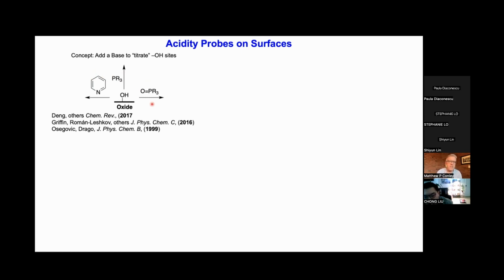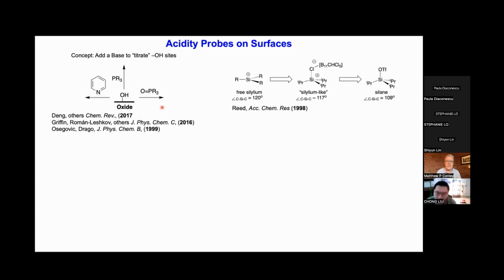Another method that we're interested in, because these are single point measures, but they don't give you all of the information you want, because you get to a point where you protonate the phosphine irreversibly, and then you're losing some characteristics about the ion pairing. So one thing we've been working on here is using a different chemical shift scale to give us some information about how an oxide would form an ion pair with an organometallic.